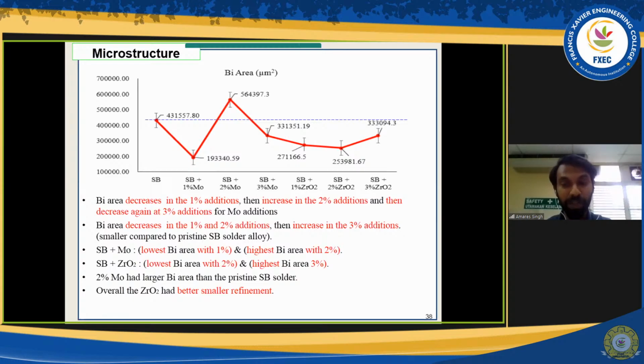We have to of course separate the area of bismuth and tin, but after the separation is done by me, there's a software that can give us the area of the bismuth. I have to do it a few times to get a proper average, and then we can say that these are consistent results. The first one is for the non-added solder. Then accordingly, I've listed the additions of nanoparticles in increasing percentage.